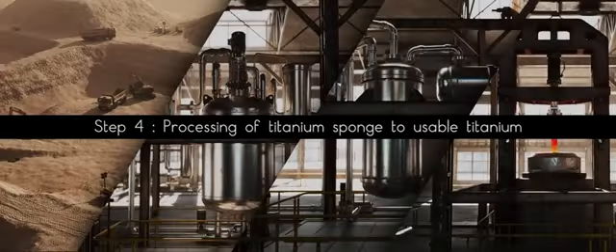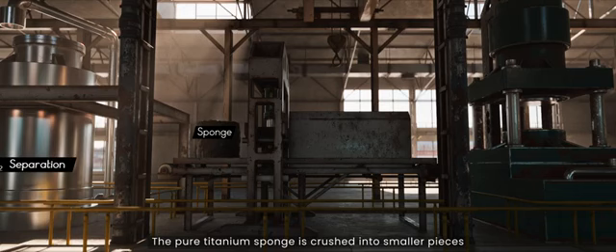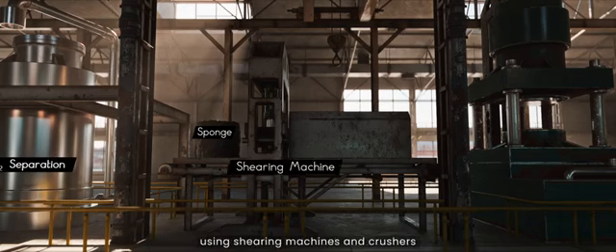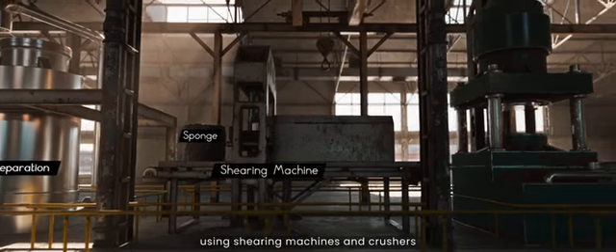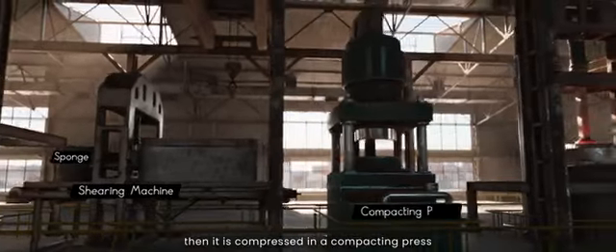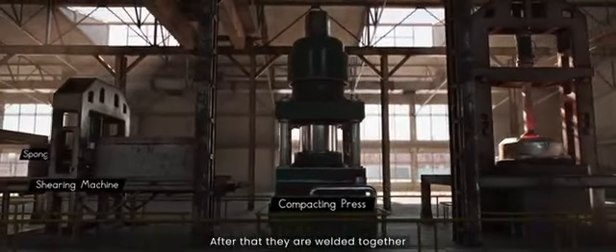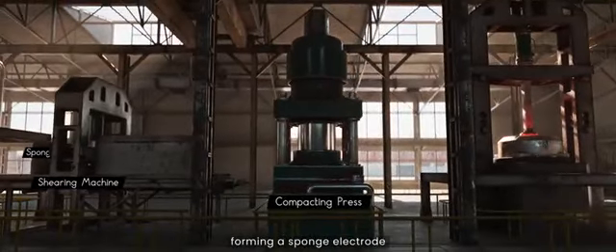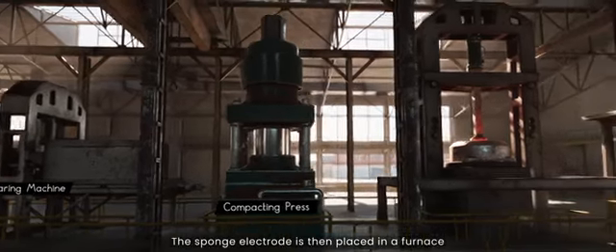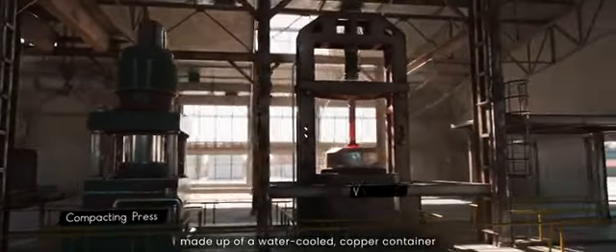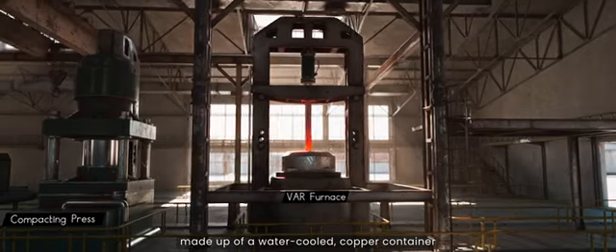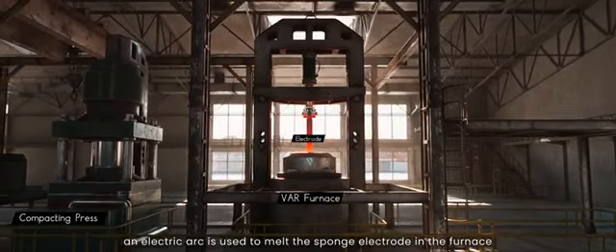Now, Step 4. Processing of titanium sponge to usable titanium. The pure titanium sponge is crushed into smaller pieces using shearing machines and crushers. Then it is compressed in a compacting press. After that, they are welded together, forming a sponge electrode. The sponge electrode is then placed in a furnace made up of water-cooled copper container. An electric arc is used to melt the sponge electrode in the furnace.